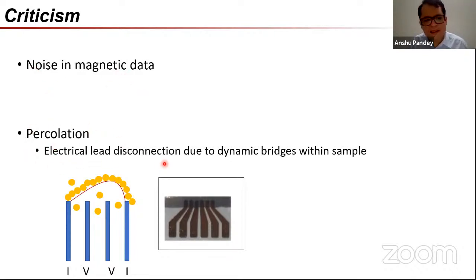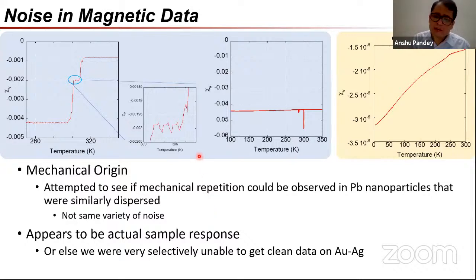Percolation essentially here in this context means that the current paths and the voltage probes become isolated. This seemed unlikely to us given that we knew in more detail how the sample was structured. But again, once pointed out, this also becomes a possibility which must be considered. So firstly, regarding noise, our initial thought was that maybe this noise was mechanical, because of some form of mechanical repetition. This could be happening because we had grains of material and these could be rubbing with each other as we went through a thermal cycle. And because of that, we would get some form of a reproducible noise because the ligands were holding these nanoparticles in approximate positions and at the same time allowing for some form of a thermally repeatable plastic deformation.